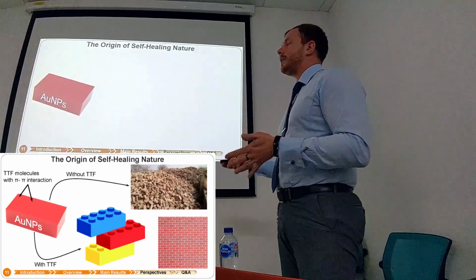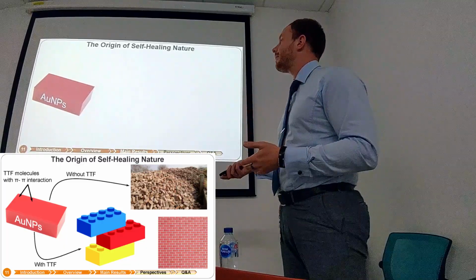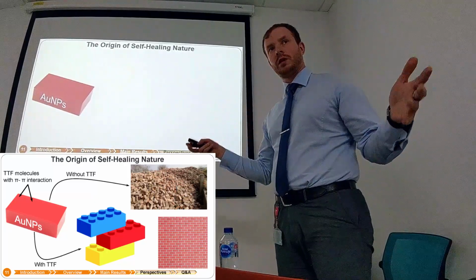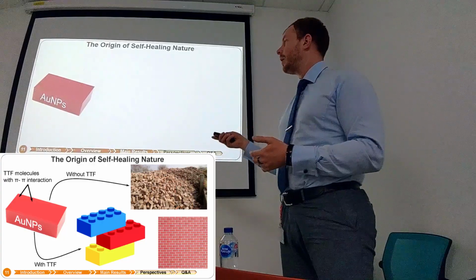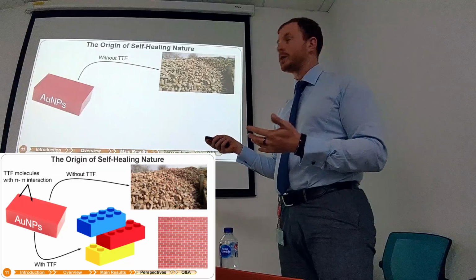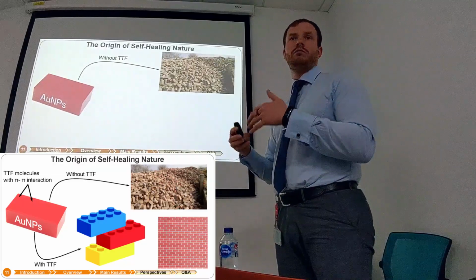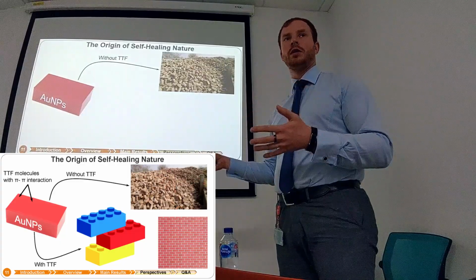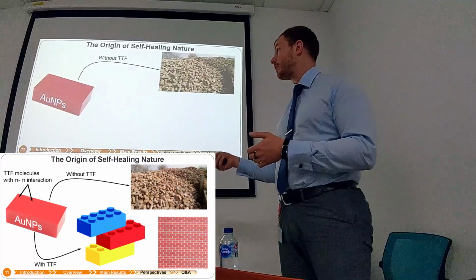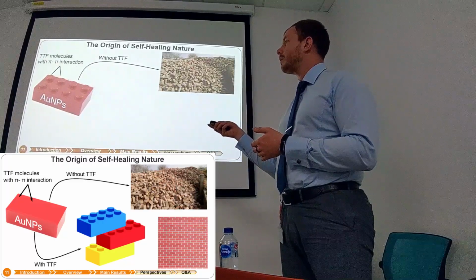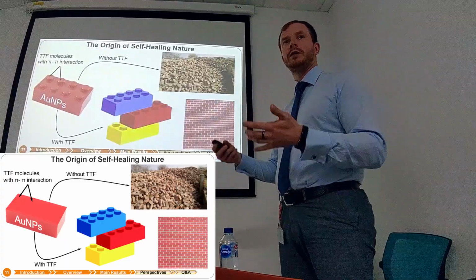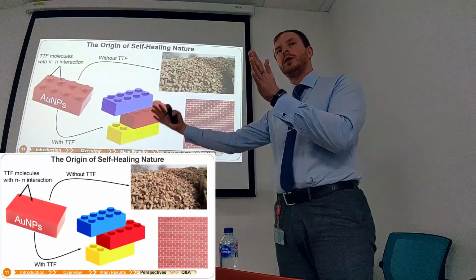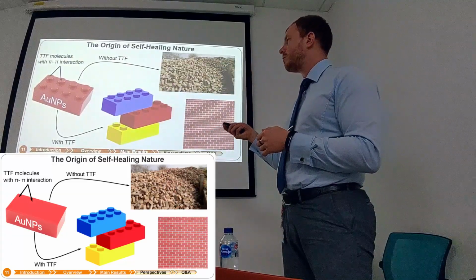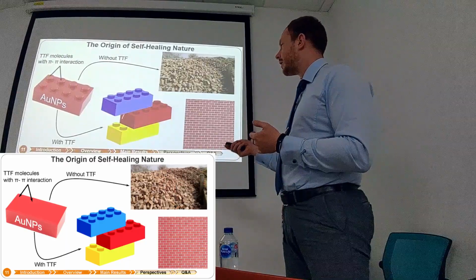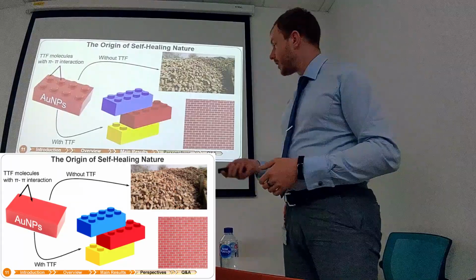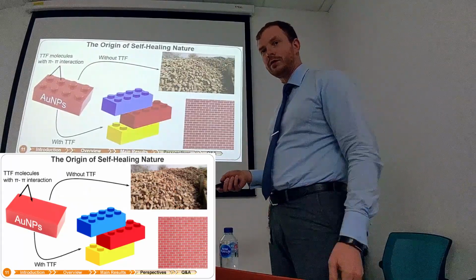What is the origin of this self-healing and of this interaction? If we try to assemble just nanoparticles, we have bricks, right? We try to build a wall out of the bricks, and we finish with crumbles. So what you saw when you add salt to a gold nanoparticle solution is a black crumble at the bottom of the pot. But if you add TTF molecules with a special pi-pi interaction between them, so they can stack one by one, then those TTF molecules work like Lego bricks, and with these Lego bricks you can already build a wall. Actually, I need to change this picture for China, for the Great Wall.